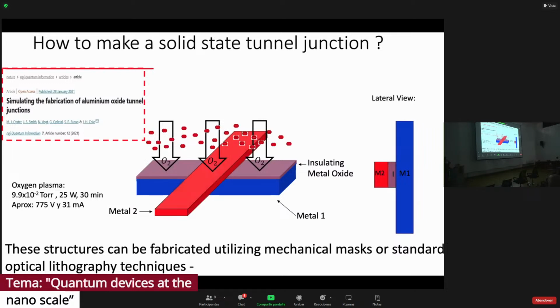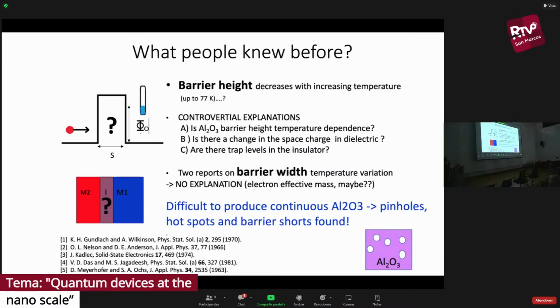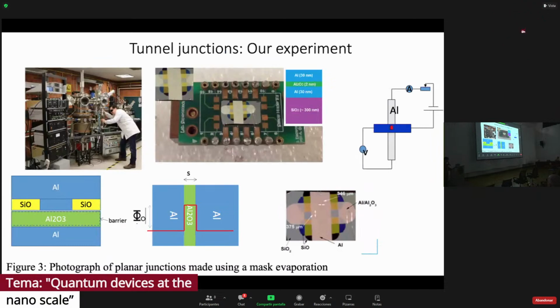Like the barrier height that changes with temperature. So we grow these tunnel junctions, and here you can see the cross of the tunnel junction. The important thing about this device is that all of this is made in situ, in the e-beam evaporation system. You put everything on the substrate, and then you fabricate everything inside. And you do this through a shadow mask, so you can produce these nice tunnel junctions.